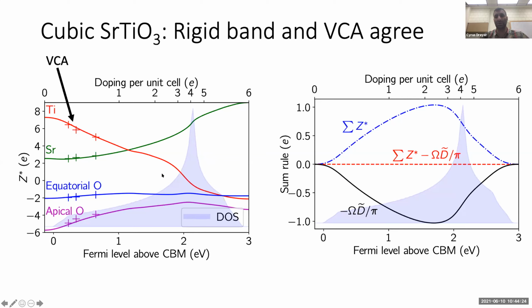The solid lines are using the rigid band approximation, and you can see that they follow each other quite well, indicating that a lot of the response properties are not changed too much versus their insulating counterparts. We also see that the Born effective charges change significantly across this, albeit extremely large, doping range. But if we sum them together, the Born effective charge sum rule is satisfied at all points.